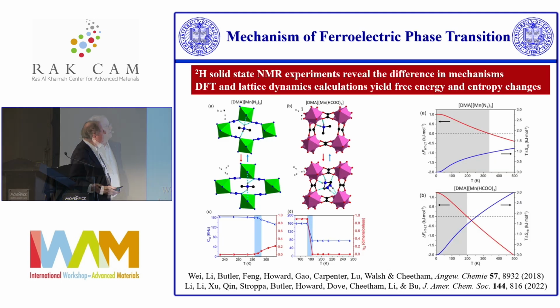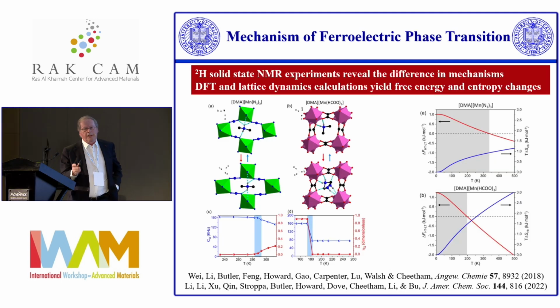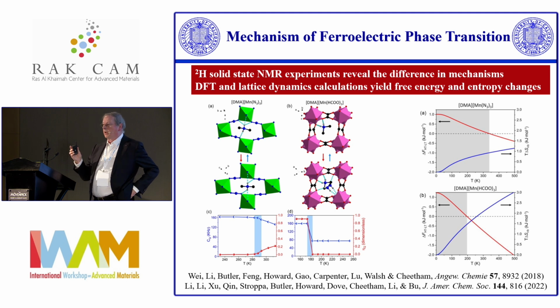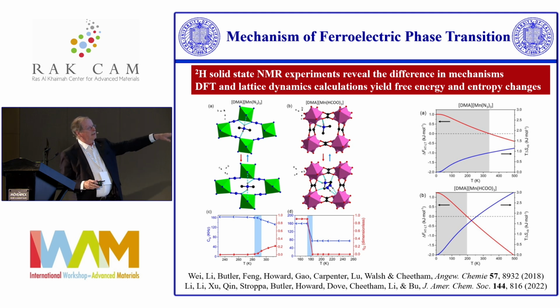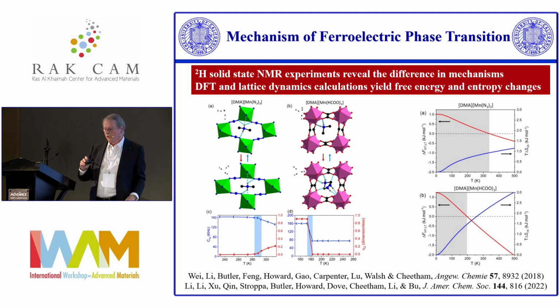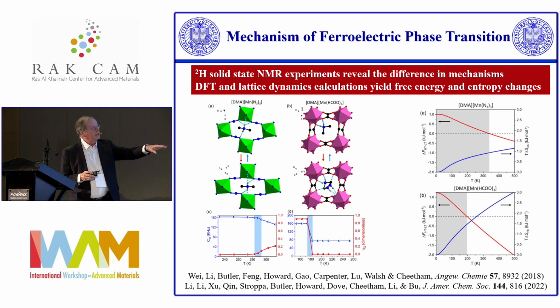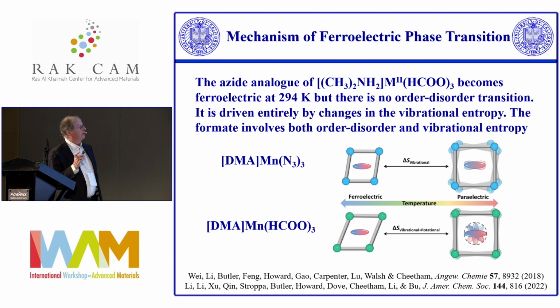And then we've done all sorts of things on this in the meantime, but one of the things we've done quite recently is to look in detail at the phase transition and the precise mechanism of the phase transition. And I'm not going to talk about the details. This is just to show you that we did deuterium NMR on this as a function of temperature. And we also did DFT calculations and lattice dynamics on it so that we could calculate the free energy and the entropy. But there's an interesting thing about this, which is the following.